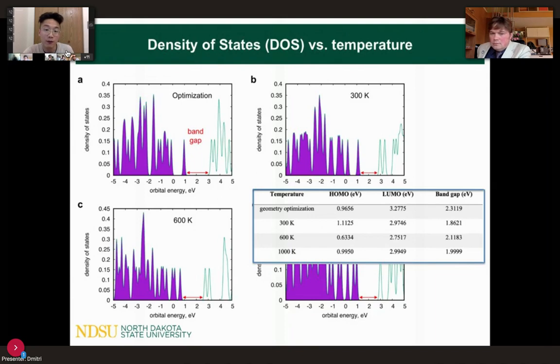If you look at the first and the last column, actually there's no obvious correlation between the temperature and the band gap. Probably due to the reason that the cellulose nanocrystal is kind of an insulator. Probably there's no significant correlation between the temperature and the band gap, compared to a semiconductor, where the band gap would decrease with increasing temperature. Next, please.